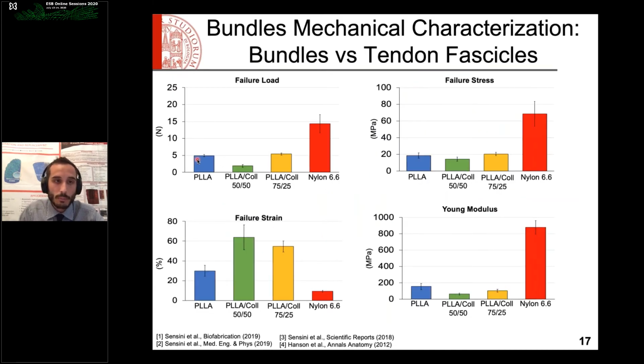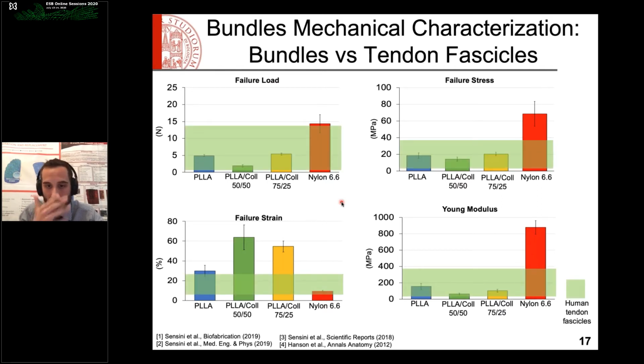Here I show you a comparison of the mechanical properties of the different bundles in terms of failure load, failure stress, failure strain, and Young's modulus, compared in the green bar with the average values of tendon and ligament fascicles reported in literature. As you can see, for the nylon 6/6 we had higher values of Young's modulus and failure stress compared to the tests in literature, and for the PLA and collagen blend we had slightly higher values of strain at failure.